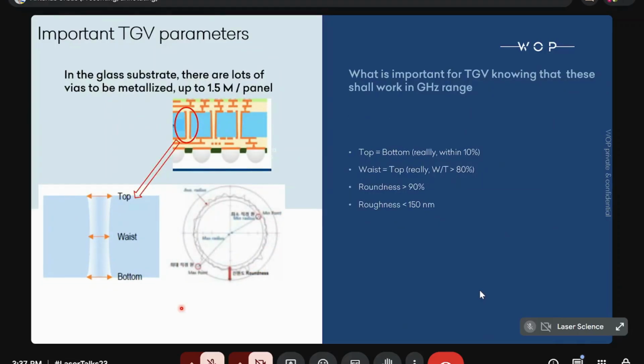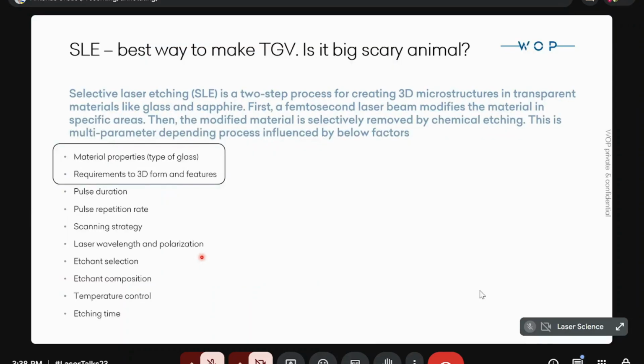So if we go to TGV, what is important if you want to go to the market saying, hey, I can make TGV, what will they ask you? As I mentioned, we have to take into account that it will work in the gigahertz range. So the form should be as smooth as possible, meaning that it should be straight, with a minimal ratio of waist to top and bottom. Top and bottom should be the same. And roundness, perfect is good, but it should be better than 90%. And the roughness of the inner wall should be 150 nanometers or better.